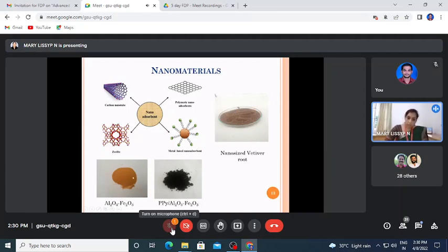We coated the alumina iron oxide nanocomposite with the polymer and did the experimental studies with both powders. We found that a higher percentage removal took place when we coated the alumina iron oxide with pyrrole monomer. So this composite we call a polypyrrole alumina iron oxide nanocomposite.